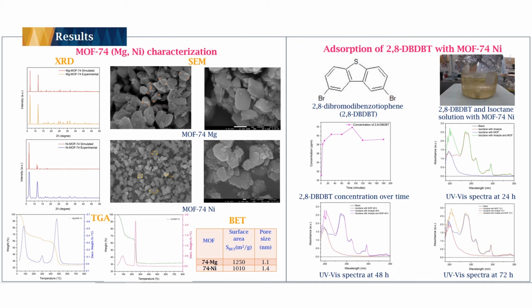For the thermogravimetric analysis, the MOF74 magnesium is stable up to 400 Celsius, and the MOF74 nickel is stable up to 250 Celsius. The surface area of the MOF74 magnesium is 1,250 square meters per gram, and the 74 nickel 1,010 square meters per gram. For pore size, 74 magnesium had a pore size of 1.1 nanometers, and the 74 nickel had 1.4 nanometers.